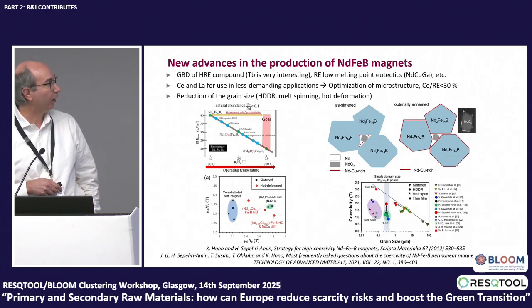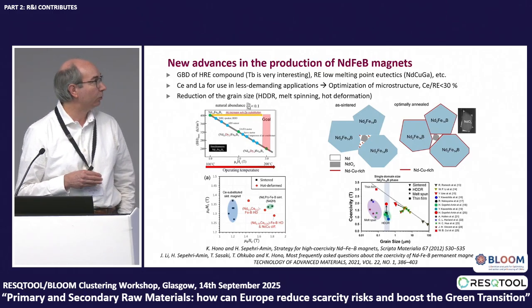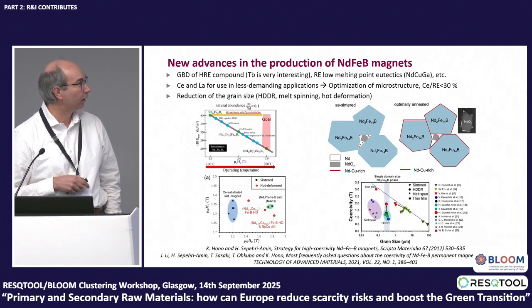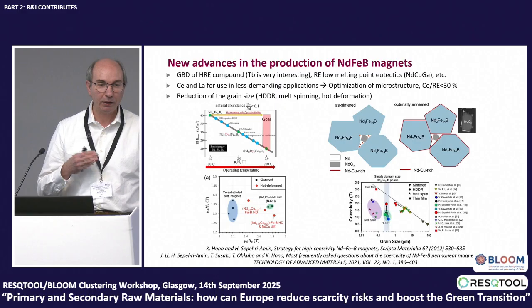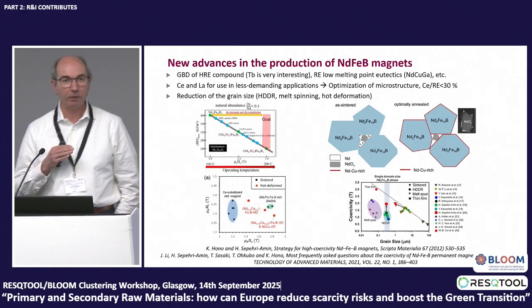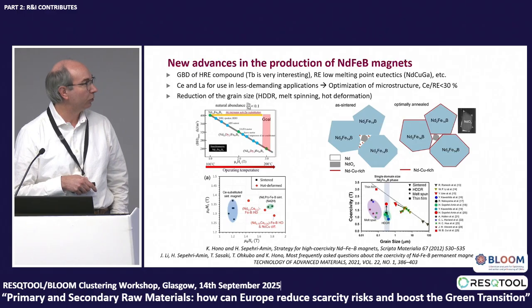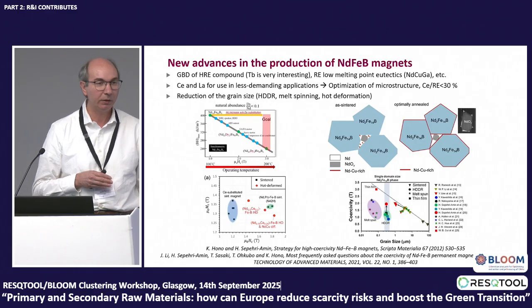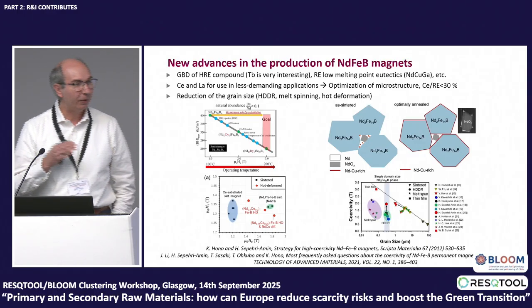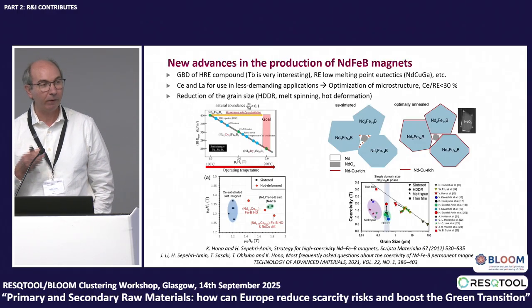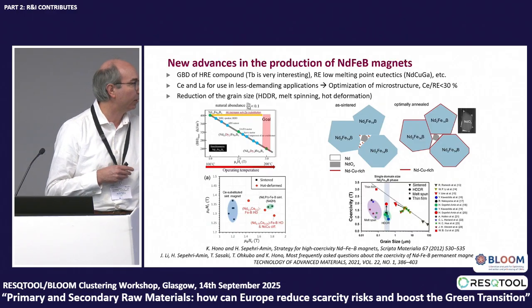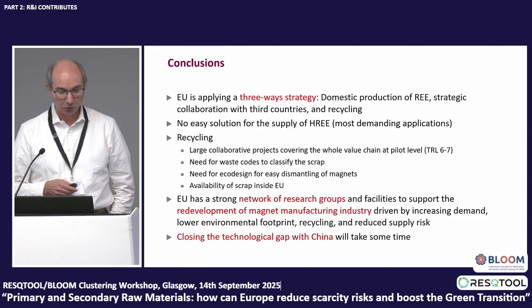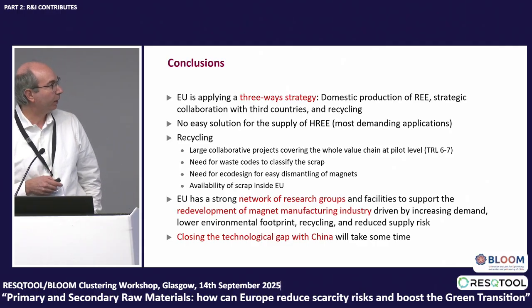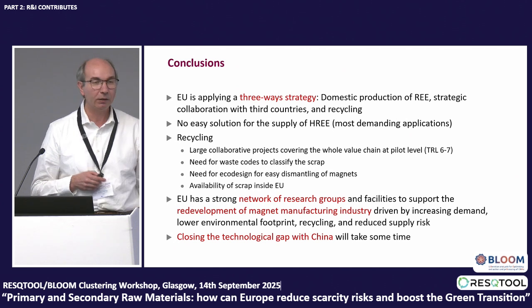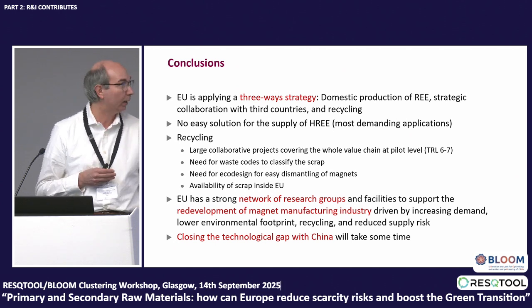And finally, the other line where we are going to see progress is in the introduction of cerium and lanthanum, but with the idea of not downgrading the properties of the magnets. We know that we can introduce a large amount of cerium, up to 30%, without damaging the magnetic properties too much, if at the same time we are able to optimize processing and microstructure. So just to summarize, Europe is applying a three-way strategy to mitigate our dependency on rare earth elements.